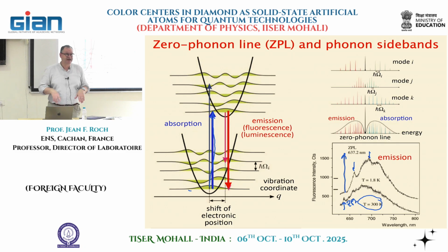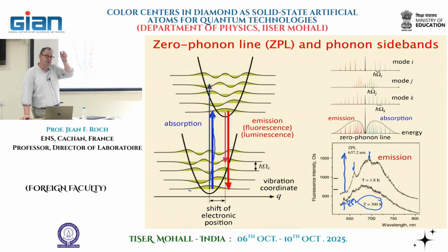But there are other defects, like the silicon vacancy center, that have narrower lines, even at room temperature. There are indeed people who have used silicon vacancy centers in nanodiamonds as practical thermometers, following exactly your idea. Yes, you're definitely right. But the NV is not so good.